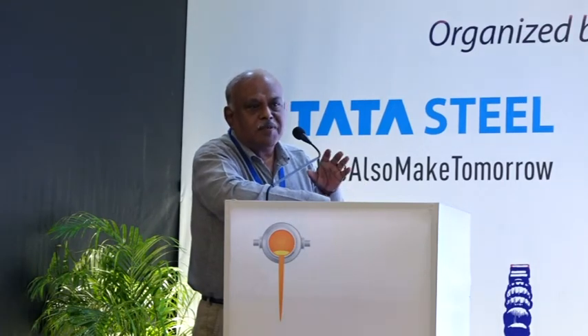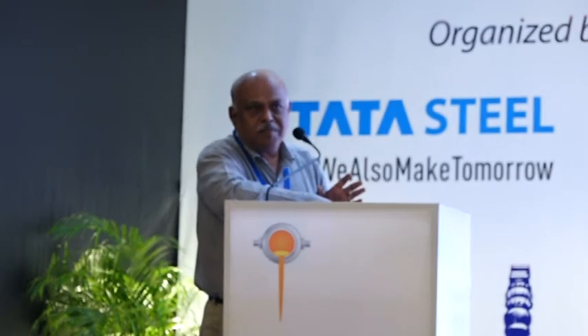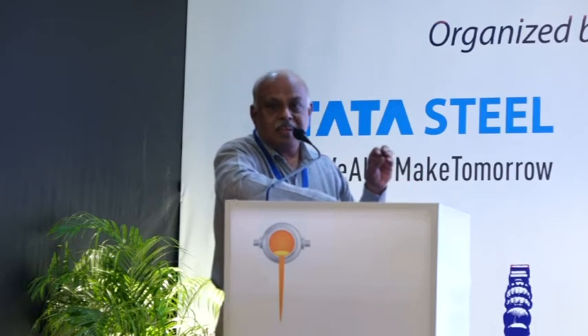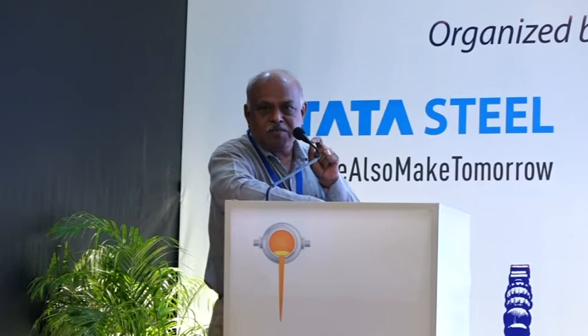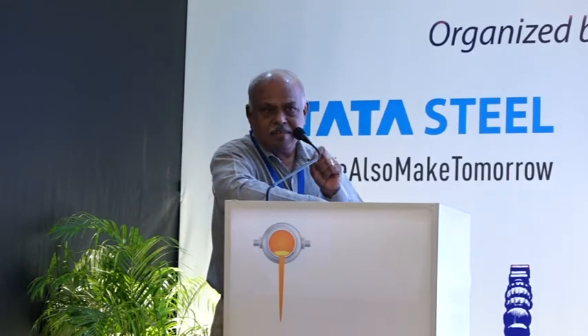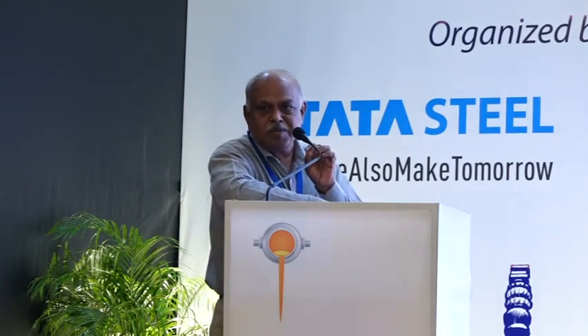And one thing is, weathering for the coarse aggregate is a must. Without weathering, you cannot sell. That's very clear. And our estimate of weathering is at least 1,000 rupees per ton. I mean, there are various methods of weathering. The estimate which we feel is likely to be right is that the processing cost for weathering of coarse steel slag is going to be 1,000 rupees per ton.